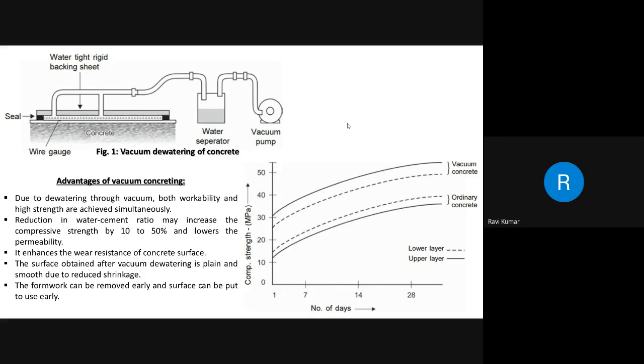We always try to restrict the water cement ratio in order to achieve higher strength. Friends, the chemical reaction of cement with water requires a water cement ratio of less than 0.38. Please make a note of it. The chemical reaction of cement with water requires a water cement ratio of less than 0.38, whereas the adopted water cement ratio is much more than that, mainly because of the requirement of workability. So workability is also important for concrete, so it can be placed in the formwork easily without honeycombs.